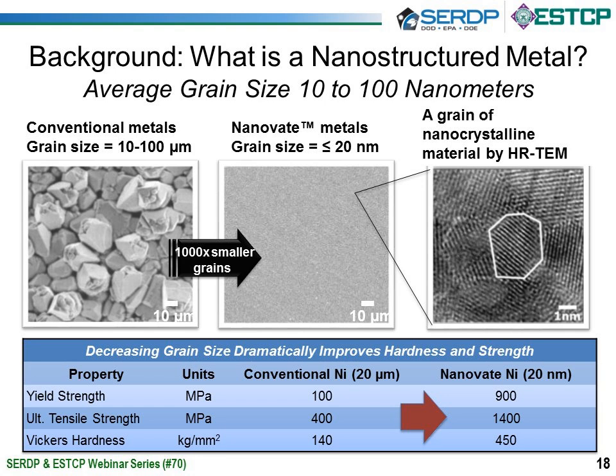So Integran's main technologies involve nanostructured materials. And we started the original project with the question of, can a nanometal coating provide a suitable replacement for hard chrome? So first off, I'll just very quickly describe what we mean by a nanostructured metal. So a nanostructured metal is simply a metal coating that has a grain size in the range of 10 to 100 nanometers. So conventional metals are crystalline and they have grains. And the grain size of a conventional metal is between maybe 10 and 100 microns. So with a nanostructured material, you just simply reduce that grain size. So the grain size is in the order of about 20 nanometers.